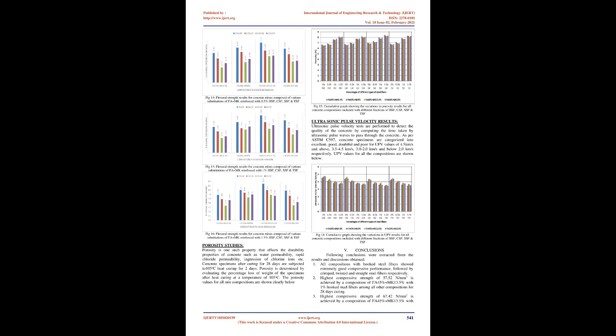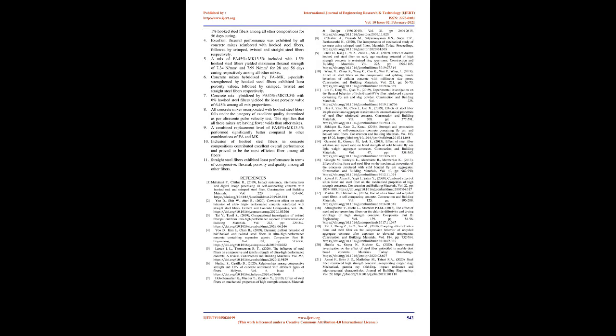Conclusions. Following conclusions were extracted from the results and discussions obtained. All compositions with hook steel fibers showed extremely good compressive performance, followed by crimped, twisted, and straight steel fibers respectively. Highest compressive strength of 57.52 N/mm2 is achieved by a composition of Fa45% plus Mk13.5% with 1% hook steel fibers among all other compositions for 28 days curing. Highest compressive strength of 67.42 N/mm2 is achieved by a composition of Fa45% plus Mk13.5% with 1% hook steel fibers among all other compositions for 56 days curing.